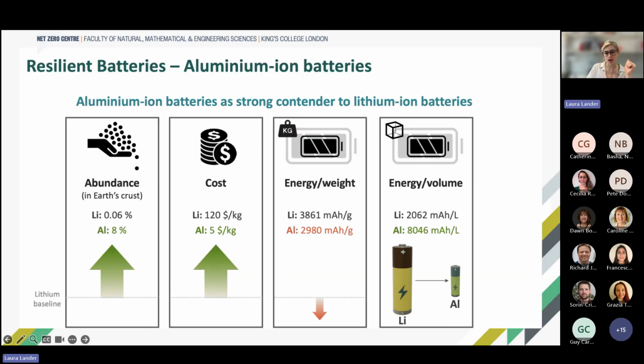And with regards to energy per volume ratio, which is much more favorable for aluminium compared to lithium, we would be able to make our aluminium-ion batteries much smaller, up to 4 times smaller than current lithium-ion batteries. And this means that, for example, in electric vehicles where we are size limited, we would be able to get much more energy in a much smaller volume than compared to lithium-ion batteries, which is a huge advantage.